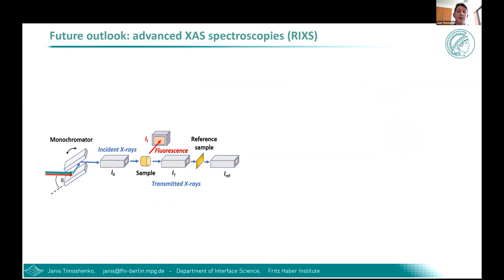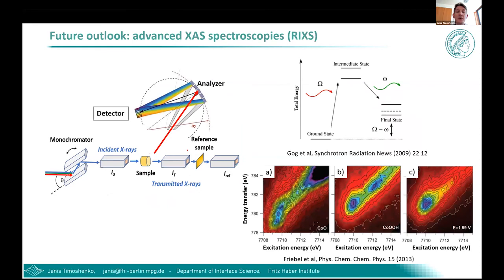And finally, the X-ray absorption method itself is getting increasingly more sophisticated. Now we can look not just at the total intensity of fluorescence, which we measure during our experiment, we can install additional analyzers and detectors and measure the spectrum of the X-ray fluorescence. In that way, we have a method which is called resonant inelastic X-ray scattering, which is basically a